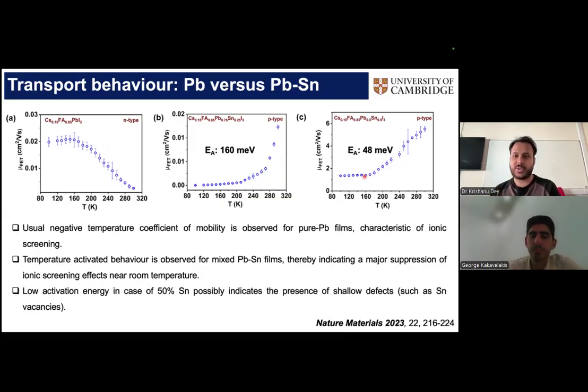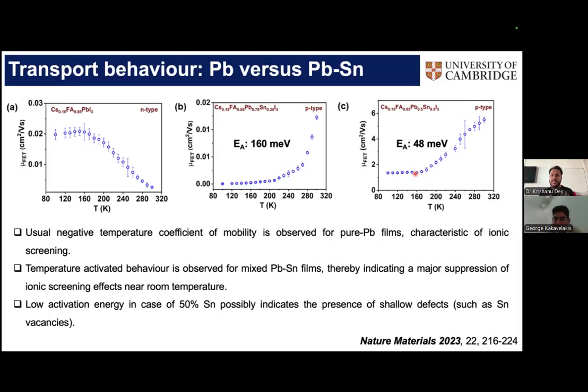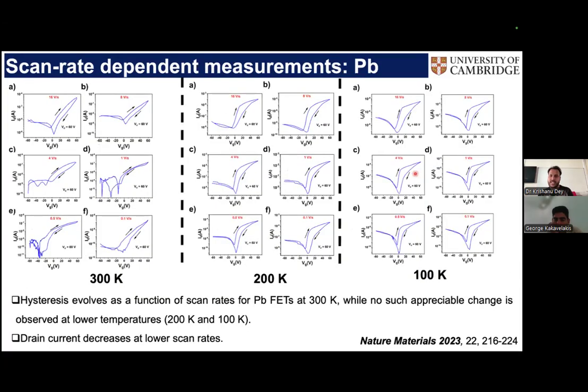Now, this was the first time we saw such behavior in any kind of 3D perovskites. And to understand that even more conclusively, we did some scan rate dependent measurements, which are known to be a pretty nice indicator of the ionic migration. So you can see at room temperature for the lead-based perovskites, as you change the scan rate from a higher scan rate to a lower scan rate, you are changing the hysteresis in these transfer curves. And then this change is basically suppressed as you go down to 200 and 100.